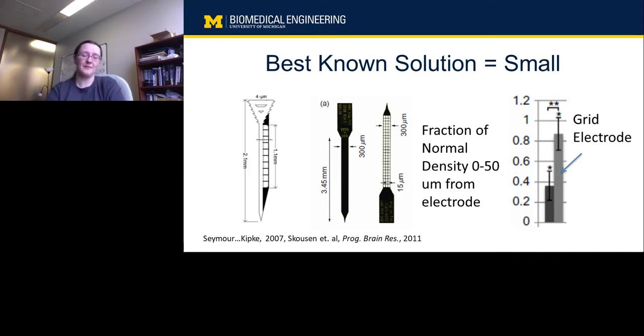So that's great. But if you'll notice, if I took those lattice probes and stuck 100 of those into the brain, they're actually doing damage on the way down. They still have the profile of a regular electrode. So that's ripping up circuitry that I would rather not rip up. And so the key is going to be how do we put something 15 microns or smaller into the brain, and do that in a way that that's the only thing entering the brain and it does very little damage on the way going in.